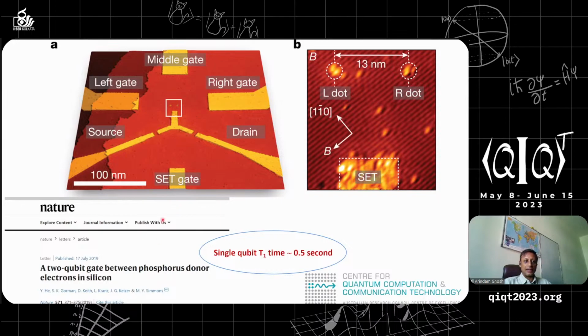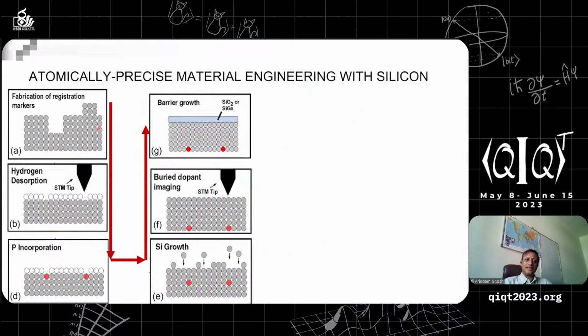We looked at their noise properties, and this work was done in collaboration. These materials are grown in a wonderful, very interesting manner. The way they grow is essentially they incorporate individual phosphorus atoms using scanning tunneling microscopy by surface passivation, and then you remove certain passivations from some points. You incorporate phosphorus atoms, then you grow silicon on top of it, and then you have essentially silicon exactly where you want. Okay, so this is how the qubits are made.